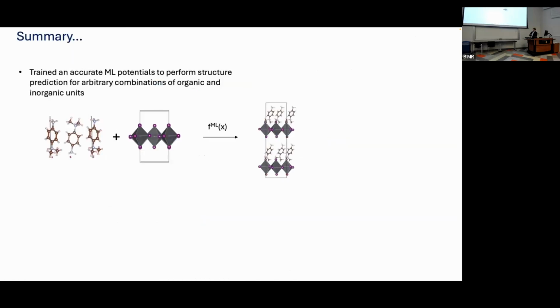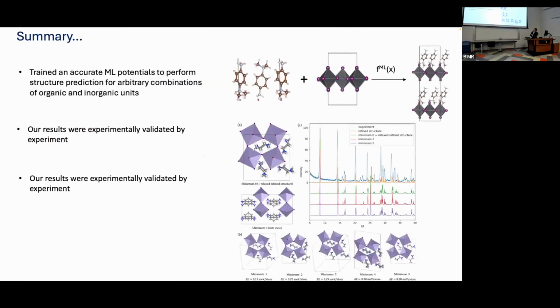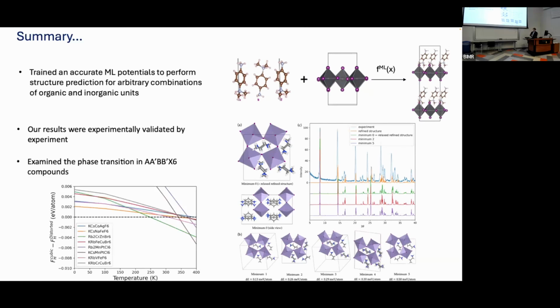Okay, so with that, I'd just like to summarize. We used machine learning potentials to predict new ground state structures of complicated organic-inorganic materials, which were subsequently validated by our experimental colleagues. That gives us hope that we have an accurate method, but it also has led to more questions about the diversity of these phases, which is not inconsistent with what we see in the local disorder. So this question about the disorder of the materials that's available versus what's actually present versus what's actually observed experimentally is quite complicated, and we're still trying to unravel and tackle it.